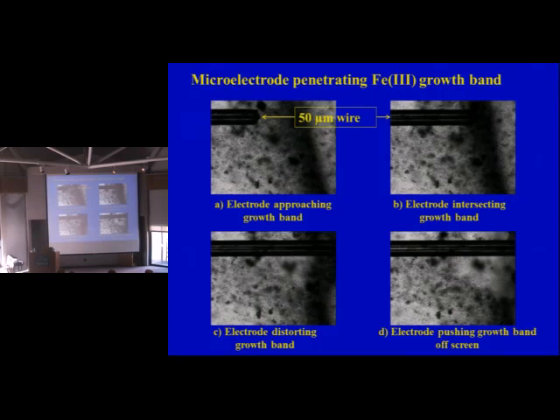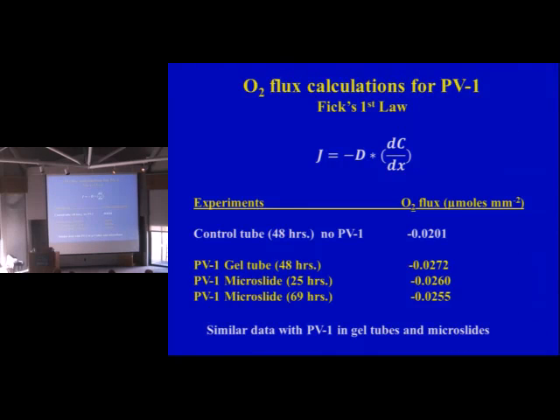So this has been taking a long time to figure out exactly what's the best so that we don't have some of these disruptions, but it's giving us an idea. But even with that in mind, if we set up a gel tube with the same type of cell counts, this is the flux of oxygen without organisms present, for a control tube. The white has no organisms. The gel tube here, here's your oxygen flux. And then the two oxygen fluxes calculated from those two profiles really agree very well with the gel tube. So we know that what we're doing with these slides is similar to what we do in a gel tube. Okay, so that was nice because that said we're on the right track.